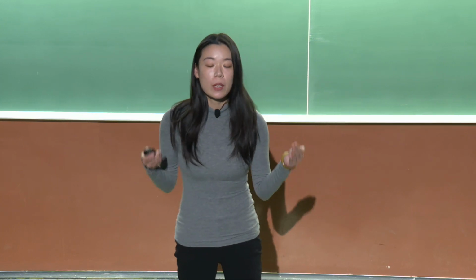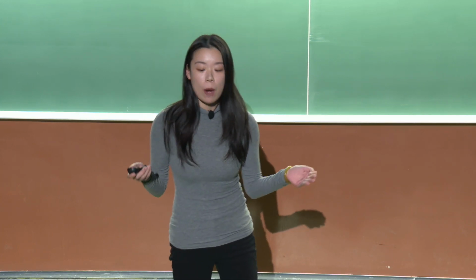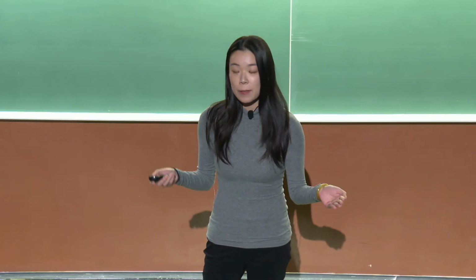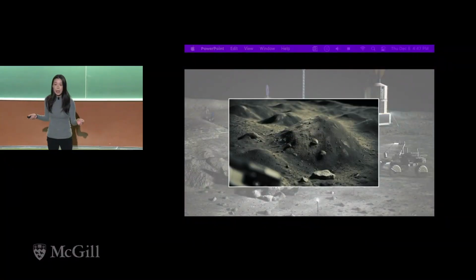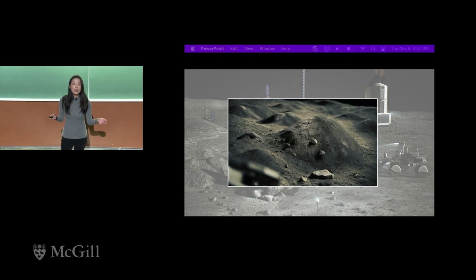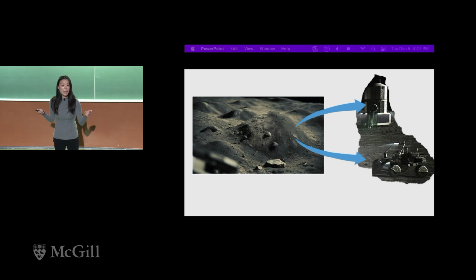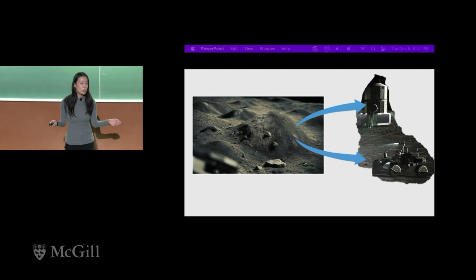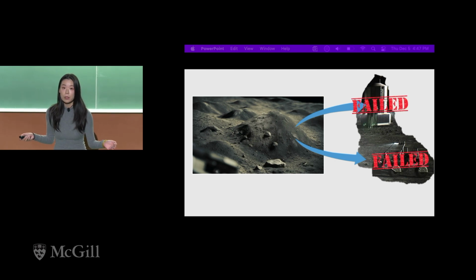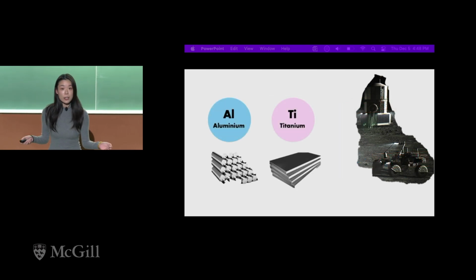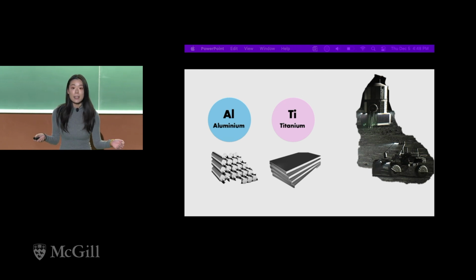One major challenge currently in the outer space is that there is a huge amount of lunar dust. These particles are super sharp and they are fast moving, traveling as fast as a bullet from a gun. Now imagine that the transporters are being hit over and over by thousands of bullets. This will cause severe damage and eventually lead to failure. Aluminum and titanium alloys are commonly used materials in space transportation applications due to their light weight. However, these materials are too soft for long-term durability.